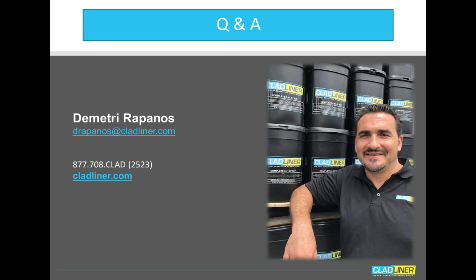So in the case of Brunswick, Georgia, we first did a restoration with the Clad Restore, whatever thickness that requirement was. I think that one was probably over an inch. And then we did a 1/4 inch of the Cladliner over the top of that. In Bremerton, Washington, the conditions allowed, so we just went directly with a 1/4 inch application of the Cladliner. In most cases, unless the conditions are very rough, a 1/4 inch will cover most rough edges, and as a result, a 1/4 inch of Cladliner is all that would be needed as a one-shot application.